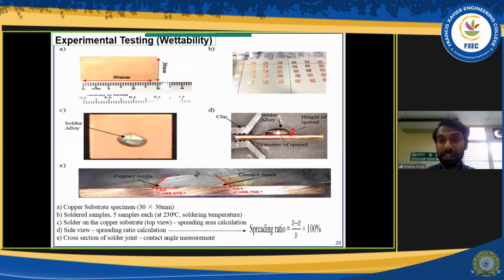So what are the experimental testing that I've done? First is wettability. What I'll be looking into for wettability is upon soldering at 230 degrees Celsius. Why did I choose 230 degrees Celsius? It is the recommended soldering temperature in the industry. So I don't want to use another temperature and say at this particular temperature is good. I might just use what is being recommended, and we can see the result directly. So at 230 degrees, it will be soldered for 60 seconds. That means 1 minute. Then I will check the contact angle.